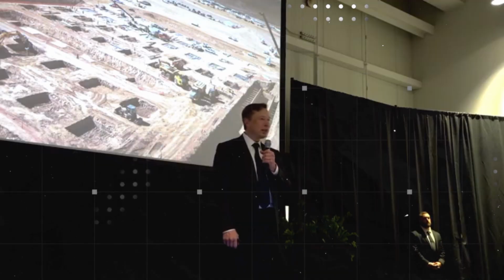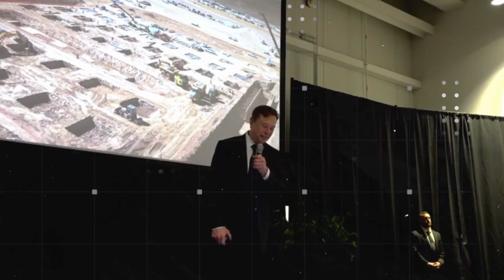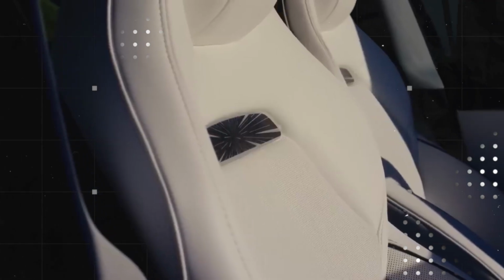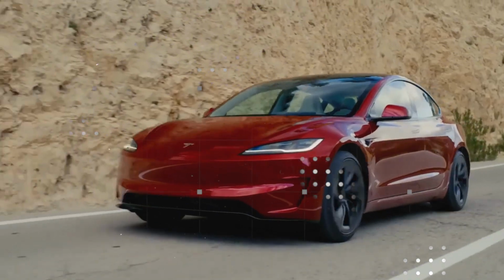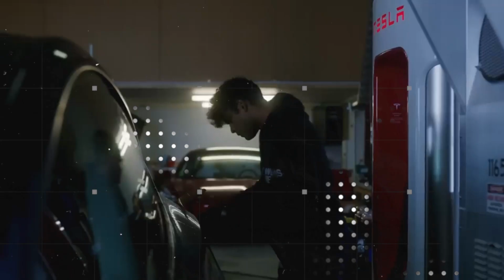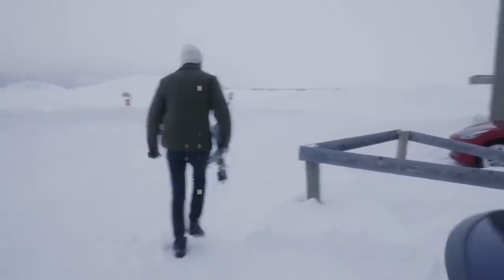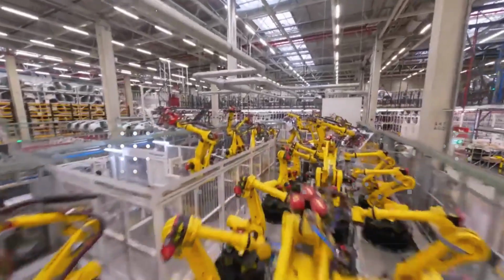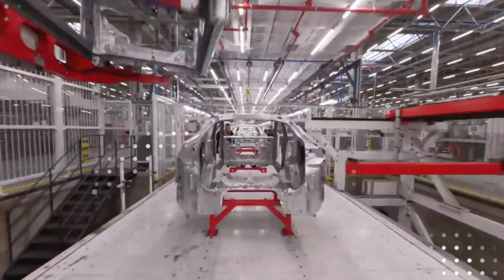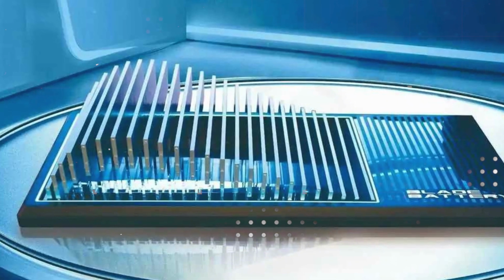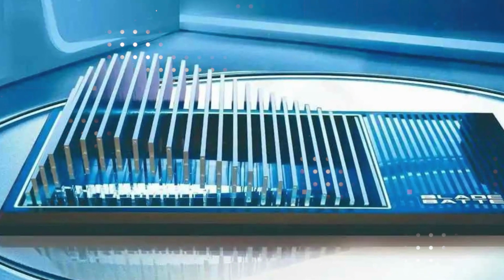The result? No corrosion, no leaks, no structural damage. After drying, they recovered between 92% and 97% of their original capacity. This means that even a flooded Tesla could be restored to service without the risk of explosion. In tropical countries or flooded regions, this resistance becomes a vital advantage.